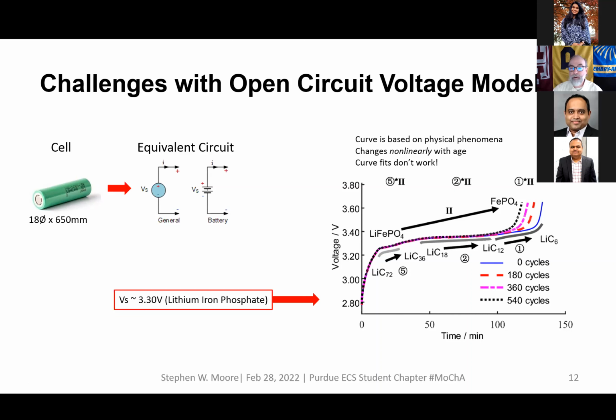And so this cell gets really tricky to model using empirical techniques, because we can measure this and we can curve fit it and say, okay, we've got this voltage curve fitted and therefore we know what the behavior of the cell is going to be. But as the cell ages, the inflection points of your curve fit don't necessarily age the same. And so at this point, we're going to have to either use a piecewise curve fit, or we'll have to use some physics-based approach to figure out what these voltages actually are and model them in real time.